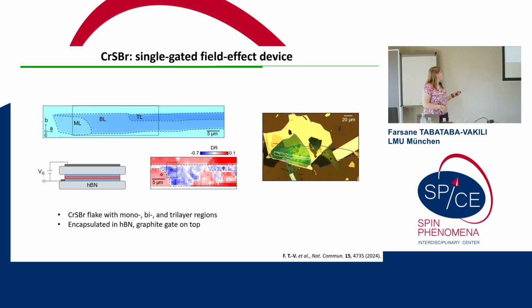So the flake is sandwiched in hexagonal boron nitride. We use few-layer graphene as a top gate and contact layer. This is an optical image of a heterostructure. And so with this gating, we can charge up the material. So the goal is to see trions and to control the properties of this material by doping.